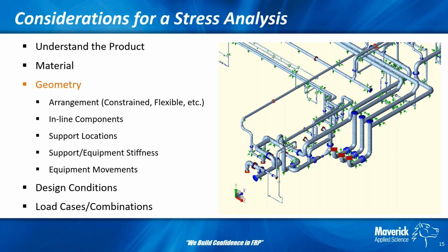If you're replacing an FRP or a steel line with FRP, then the spans are probably a little bit longer, so you're going to need to identify intermediate steel. Take note of any stiffer locations. You want to put anchors really at your stiffest locations to be able to handle the reactions imposed, and so it's not flexing while it's operating.